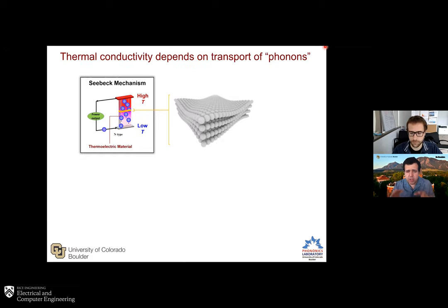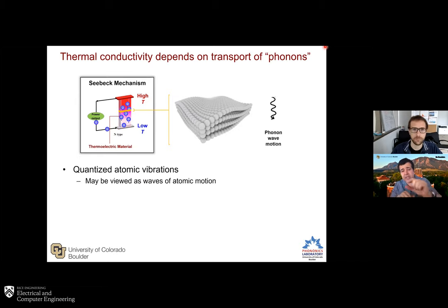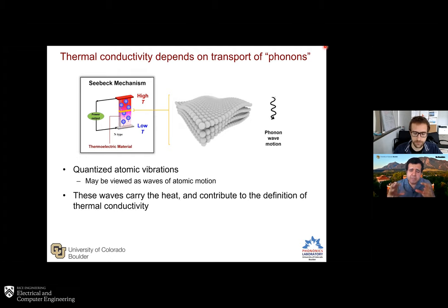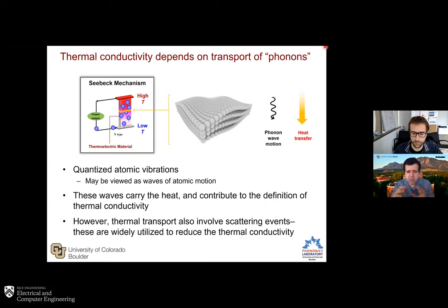So we're going to focus on the denominator part for the most part, the thermal transport. And underlying that at the most basic level is phonons. So if we take a strip in that material, we will recognize that that strip emits phonons, which of course are quantized atomic vibrations. In the context of this talk, I'll be viewing them mostly as waves. And these waves play a very important role in the very definition of thermal conductivity. However, the wave picture is not sufficient because thermal transport also involves scattering events. These are widely utilized, in fact, to reduce the thermal conductivity.